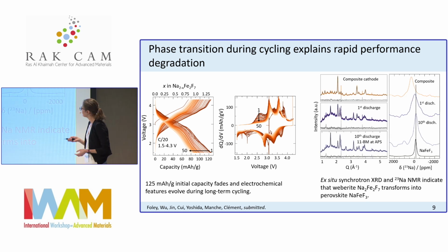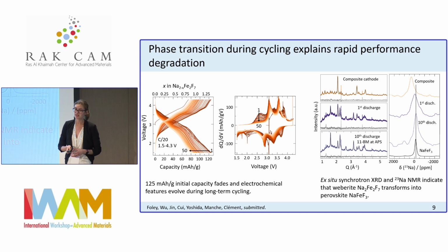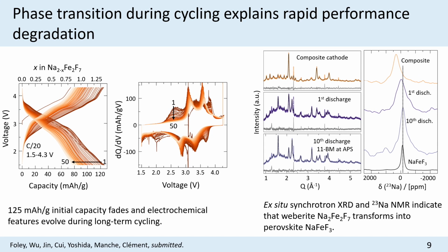So we decided, based on these results, to look a little more in detail at what is going on in our material as we cycle it for, say, 1 cycle or 10 charge-discharge cycles. These are synchrotron XRD data and then sodium NMR data shown here. Both of these data sets suggest that our initial Weberite cathode is evolving into a perovskite and a NaFeF3 material. So over time, our Weberite, which was metastable, is starting to evolve into a more stable phase.